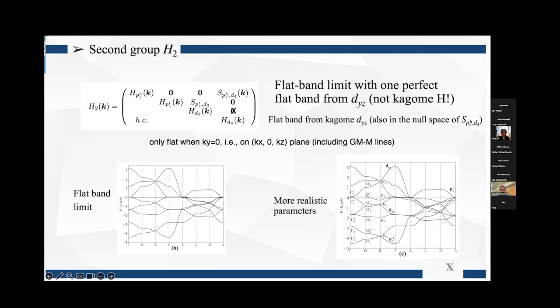So for example, if we look here, we have a flat band, and you can see it in Ricardo Comin's work, and I think Joe is also on the paper. You can see it in the ARPES of those papers, actually. There's a flat band and of course, Ming Yi, who has, I think, the best data so far on this FeGe, but you can see it on these compounds, and there's clearly some dispersion. It's very flat on some lines, and you can understand this from these Hamiltonians. There's some dispersion on the other lines, and in some of the initial data on FeSn, I think that came from Ricardo Comin's group, you can clearly see this.